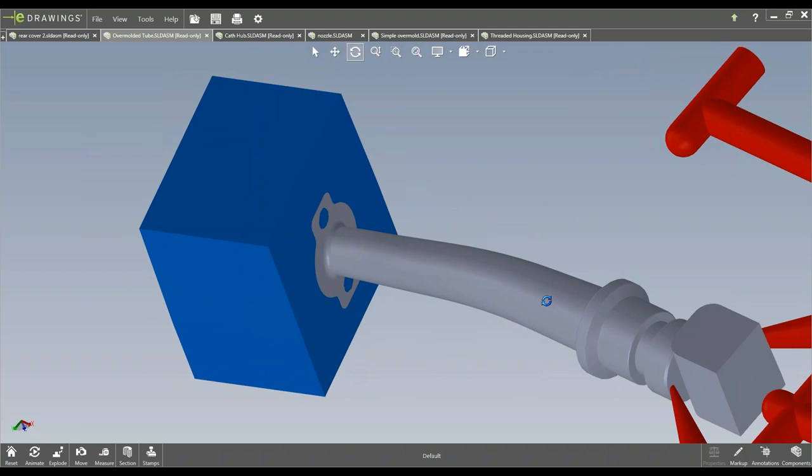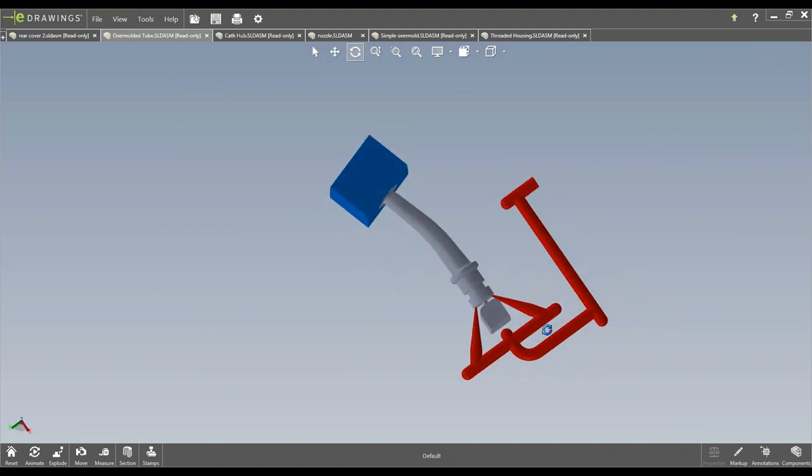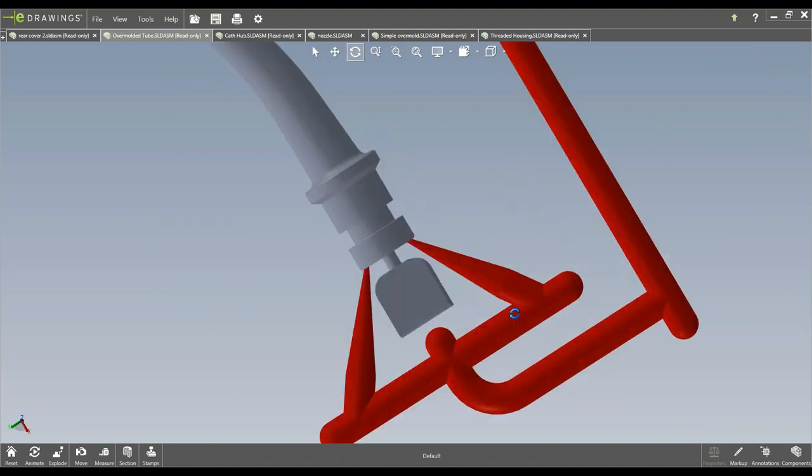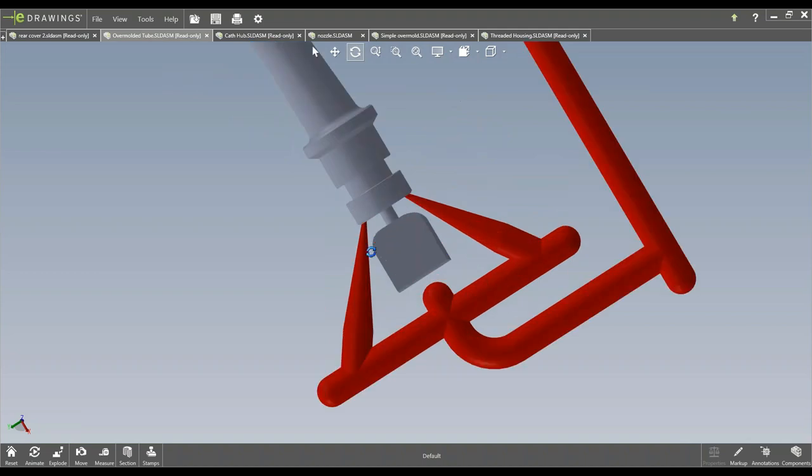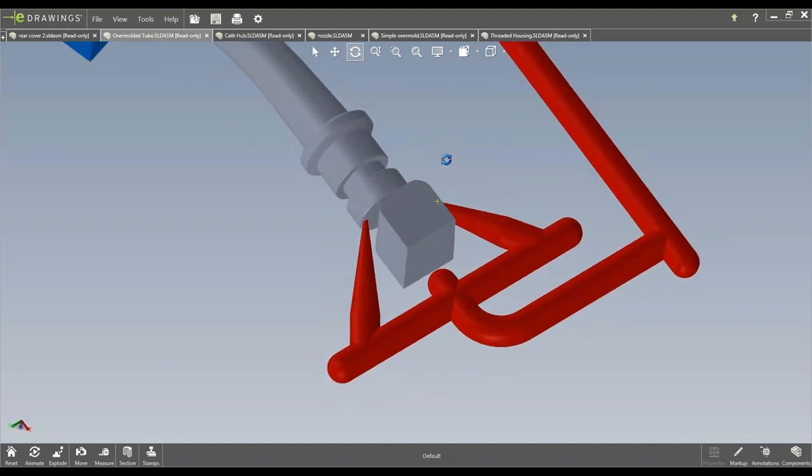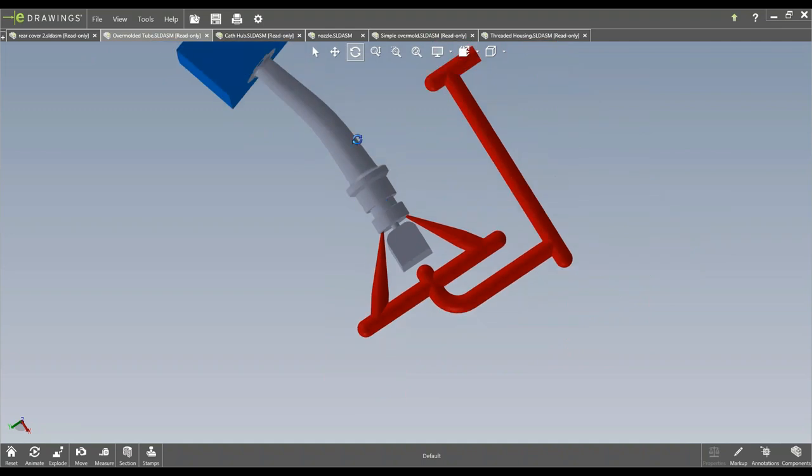So yeah, this is a pretty intricate design just due to the overmolding of that tube or that through hole. I mean, overall, just looking on the outside of the part, it looks pretty easy, but we've done quite a few iterations and this part's now in production. The gating on this one, you can see the runner system come in. So we actually put two gates in and the idea of that is to keep even pressures throughout the fill process to try to center that tube all the way down.